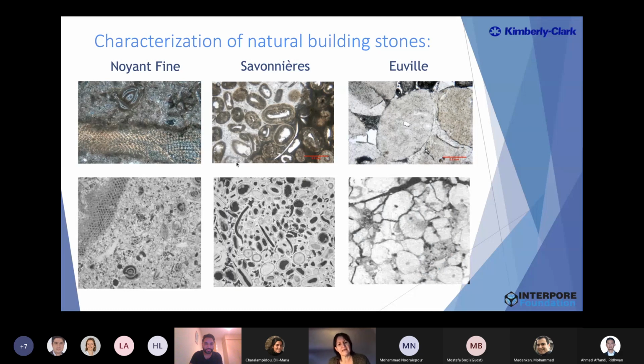If you would scan them, you would have an image like this. This is one reconstruction, one slide that you see at the bottom from a CT image. The difference is that in the upper image, first you need to make a thin section, so there is some preparation, and it's destructive. Using CT, you can just put your sample inside the scanner and look at it without any sample preparation. Also, an advantage is that with CT, you can see whatever cross-section you want, or look at it in 3D, while this is not the case with optical microscopy, where you look at your sample in 2D. A disadvantage is that with optical microscopy, you can determine the different minerals, which is a challenge when using CT. But I will go more in detail on that as well.